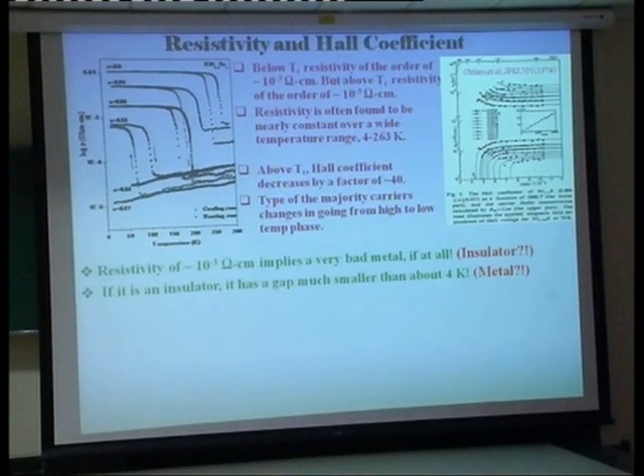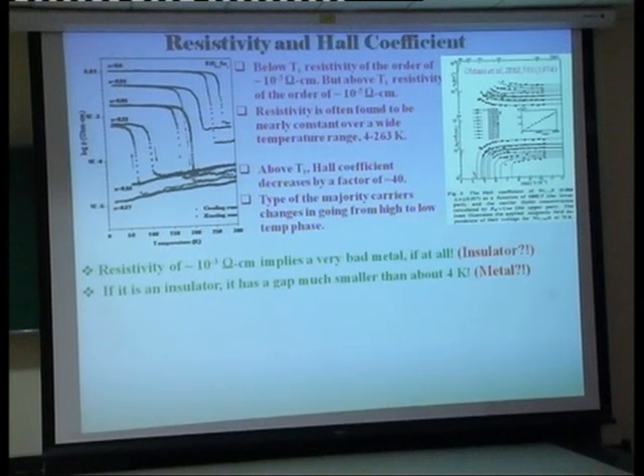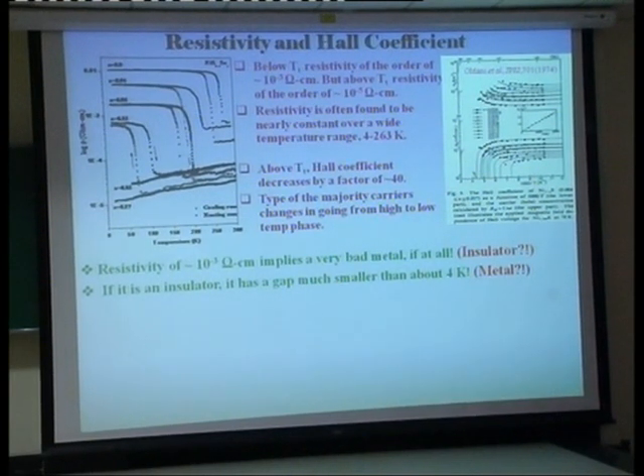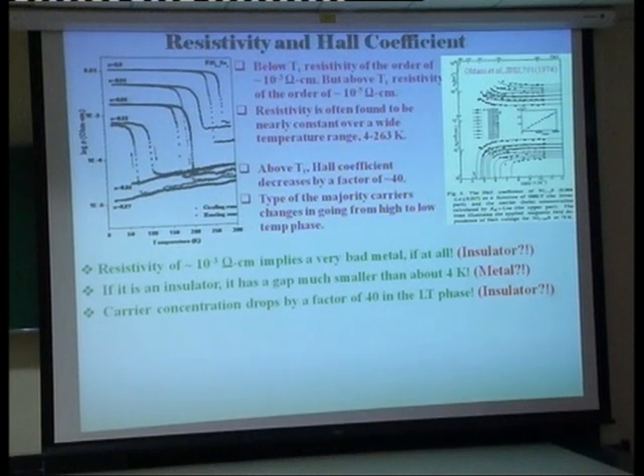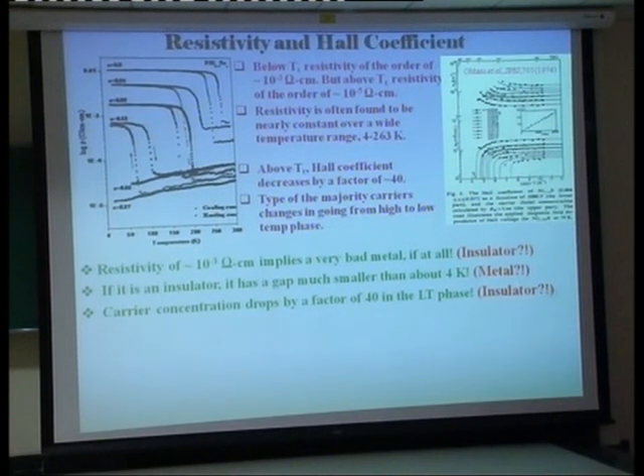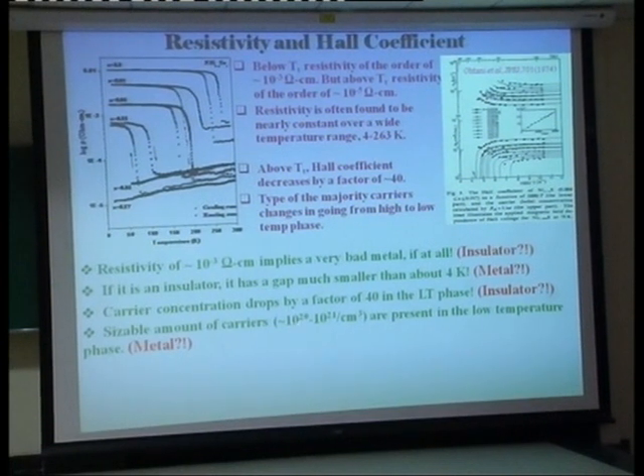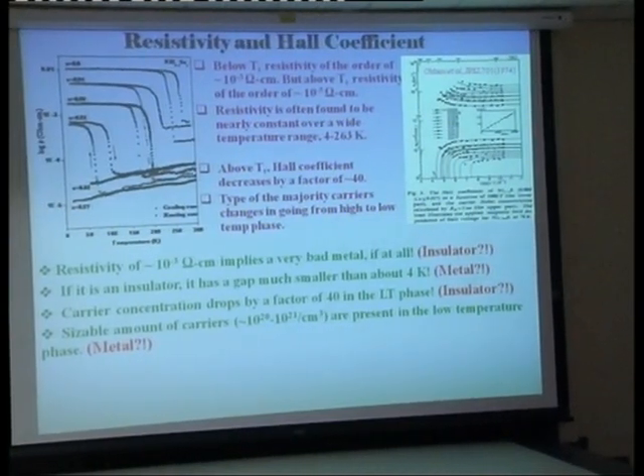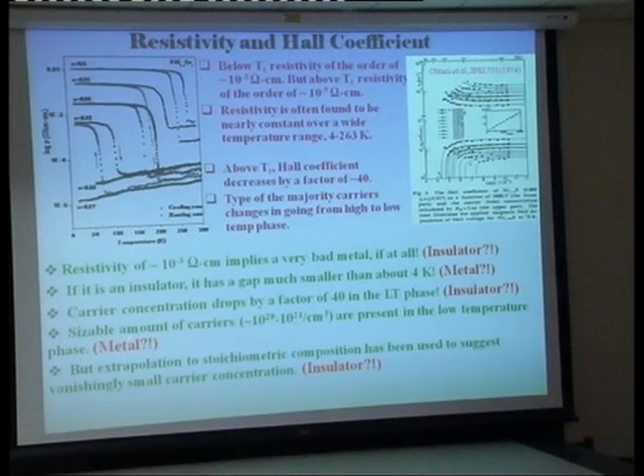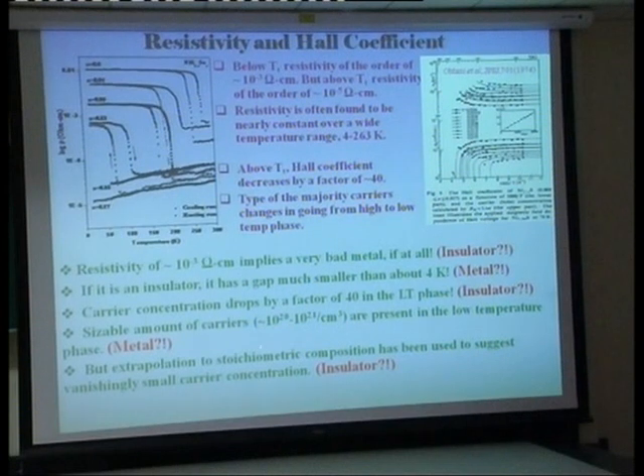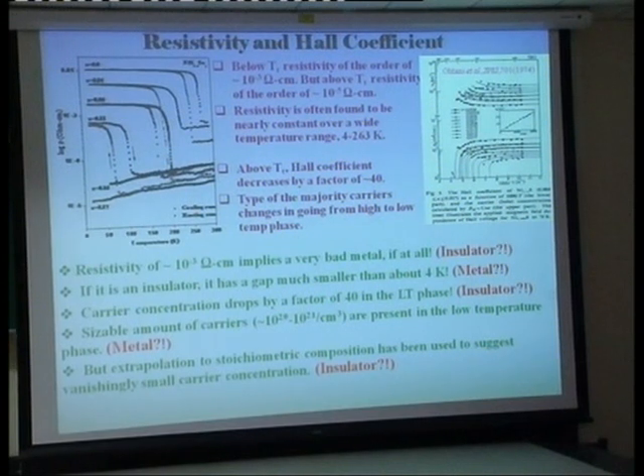So there are these basic observations from the whole data I've shown. The summary of this transport data would be that we have bad resistivity, so it could be an insulator. Well, if that's an insulator, because the temperature coefficient of resistivity is so close to zero, it couldn't be an insulator, so maybe it's a metal. But if it's a metal, then I have the charge carrier concentration dropping by a factor of 40 from the high temperature to the low temperature. That implies it must be an insulator. But then I'm left with still 10 to the power 20, 10 to the power 21 per cc carrier concentration, so it should be a metal. But then if I extrapolate this charge carrier concentration as a function of stoichiometry, or the nickel vacancy concentration, I come to a number that's very small at the end, so it's an insulator.